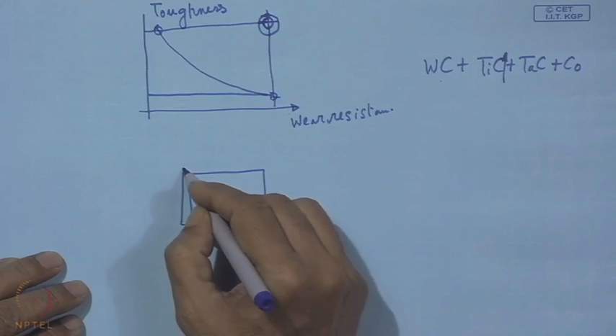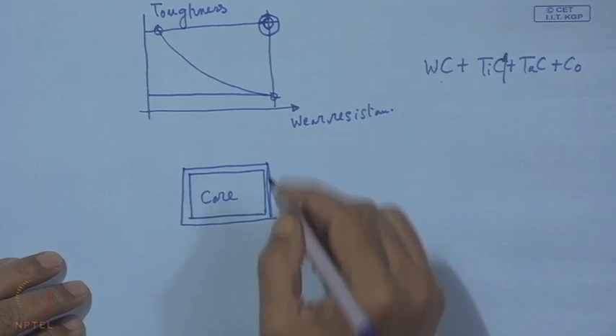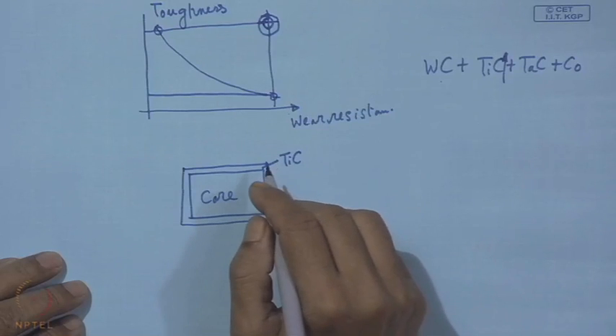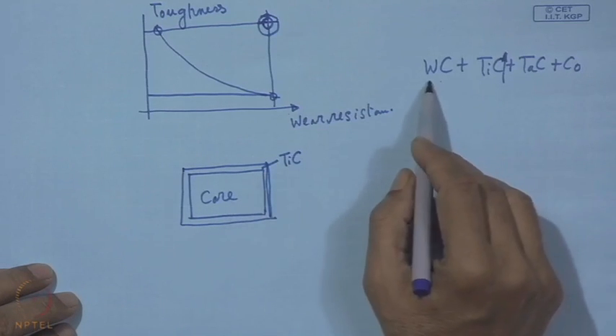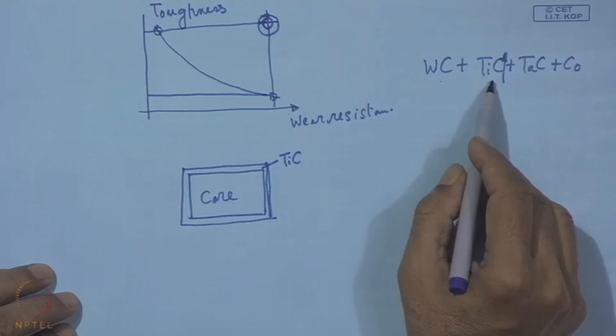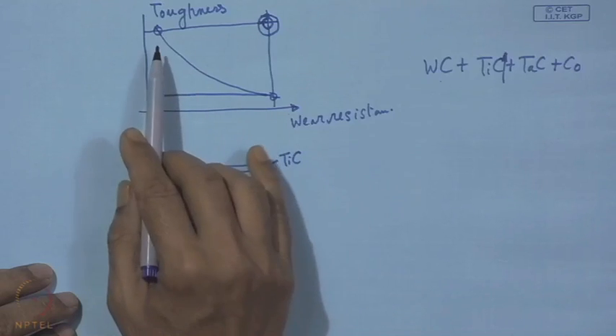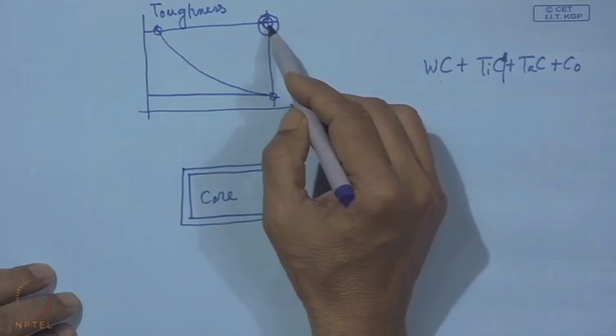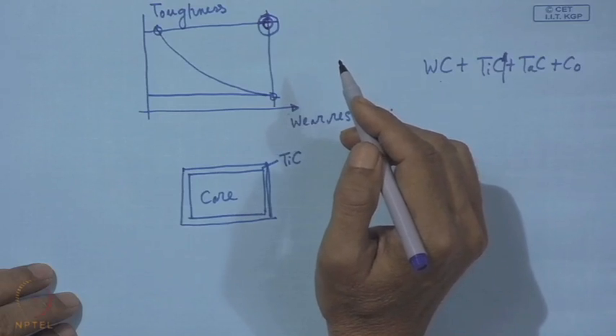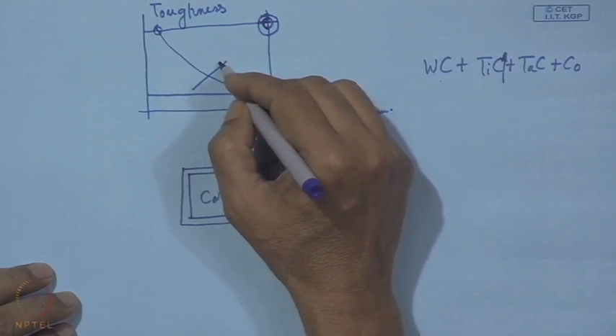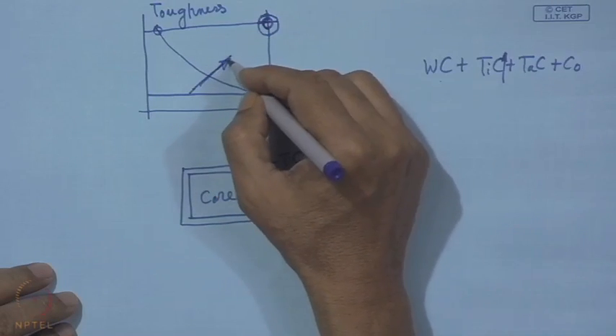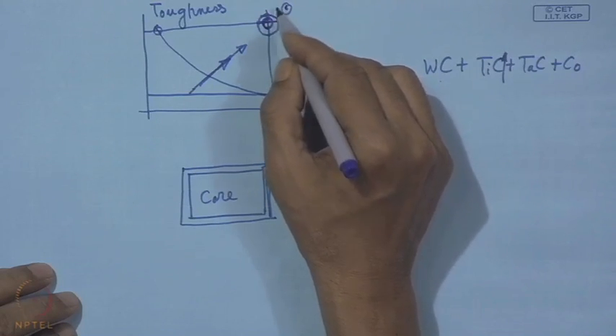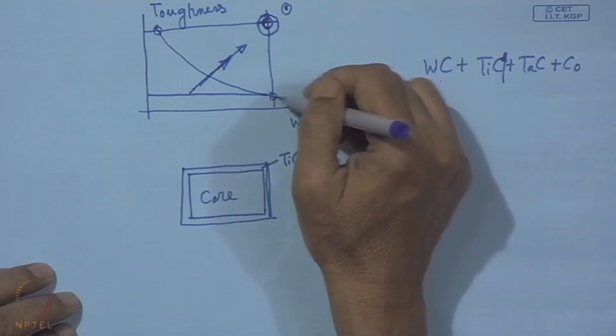In this composite approach, we have toughness in the core and a coating at the surface. If we can put titanium carbide as a surface layer giving the necessary cutting property or wear resistance, then we can have low or almost zero content of TiC inside the core. We can have the tough substrate and at the same time a surface known for wear resistance. The goal of research in this direction is always to push this curve further, getting tools with remarkable toughness and also wear resistance.